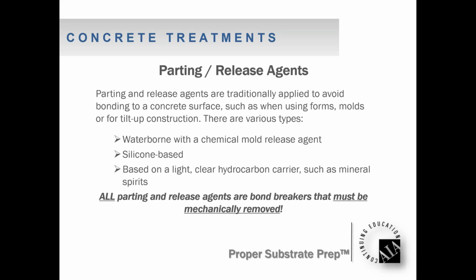So anytime there's a tilt wall project, the surface of the concrete is going to have some sort of parting or release agent on the surface, and that's so the two concrete slabs don't stick together. The problem is that parting or release agent is not going to allow anything else to adhere to that surface. Now, fortunately, with tilt wall construction, those are typically warehouse floors that commonly are just left as bare concrete, so not an issue. But if you're putting any type of coating or sealer or patching or leveling product, then certainly those parting release agents need to be mechanically removed.